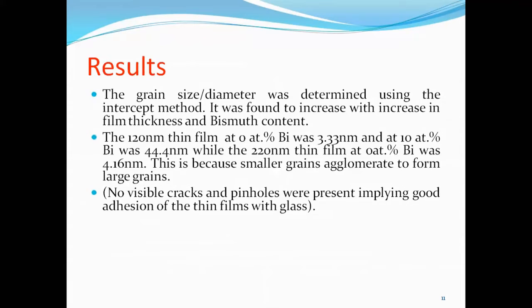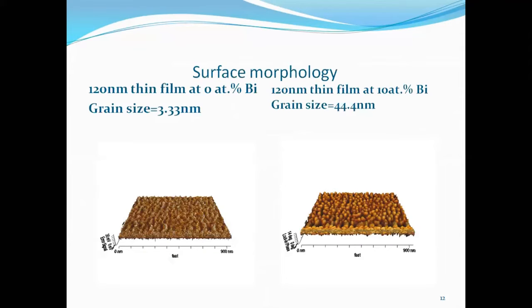These are the results. Now, this is what we discovered on the AFM photographs. The grain size or the diameter was determined using the intercept method. And it was found to increase with increase in film thickness. Allow me to go to the next slide. Yeah, this is the slide for the 2 films, comparing the effects of bismuth content.